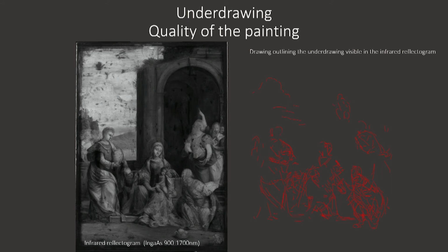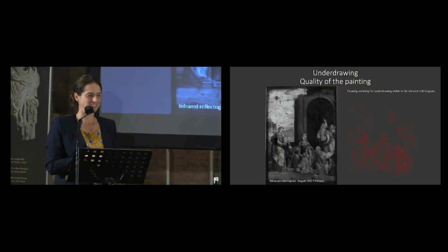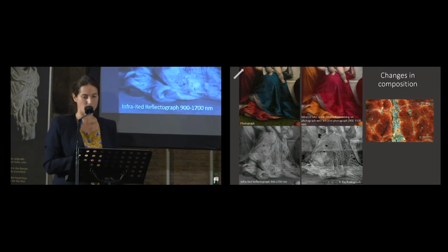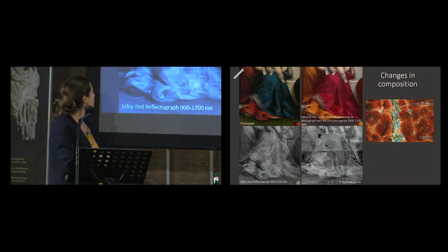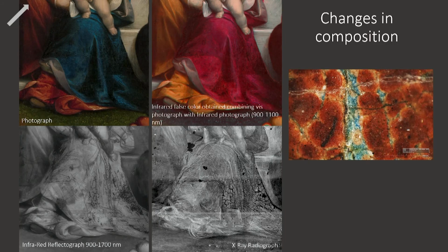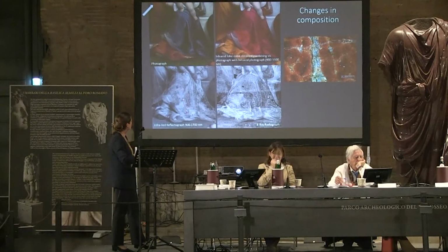The Garofalo immediately stood out as an interesting case for both technical and art historical reasons. Despite being a subject that he reproduced many times through his oeuvre, he was always searching for a slightly different composition, and in our panel there's a very tormented underdrawing with some features positioned 4 or 5 times. With the research conducted so far, we could not make sense of all these changes that continued in the painted phase, and especially I want to point at this line here, this fold, which was discarded in the final composition and that follows an underdrawing line.